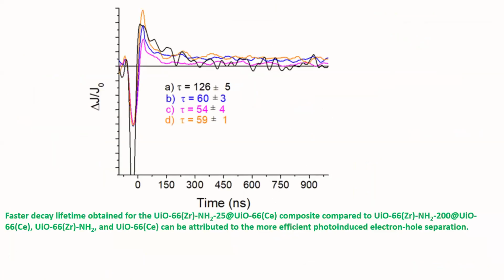So this is yet another evidence to show that the faster decay lifetime obtained for this solid compared to the other solids can be attributed to the more efficient photo-induced charge separation. And this is one of the key experiments to reinforce our experimental results.